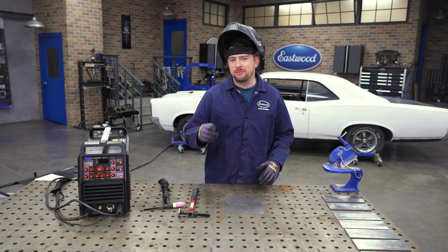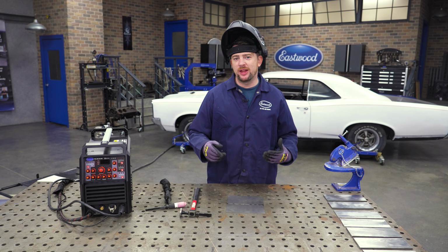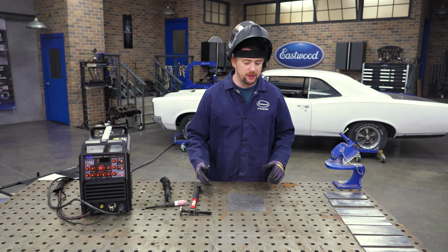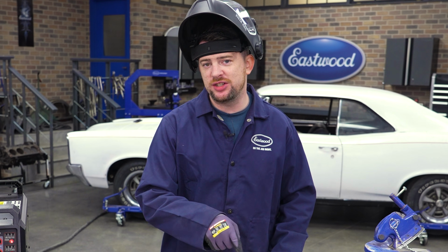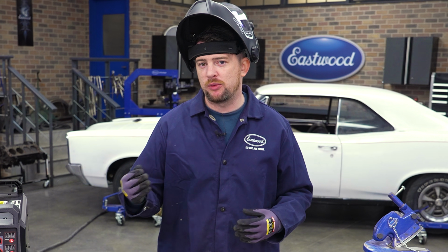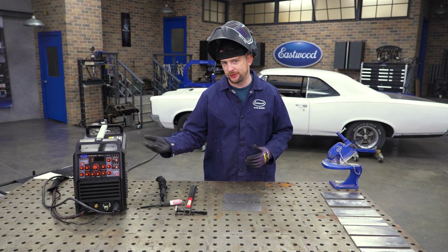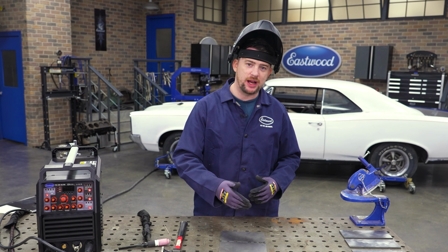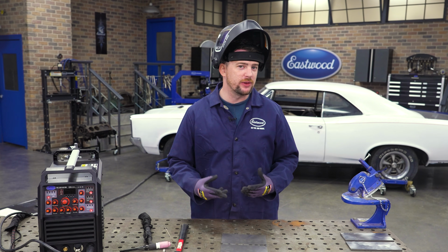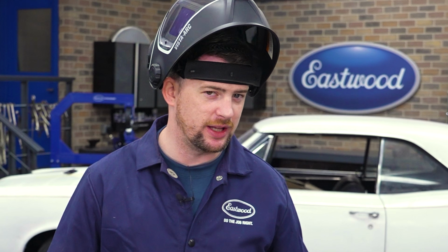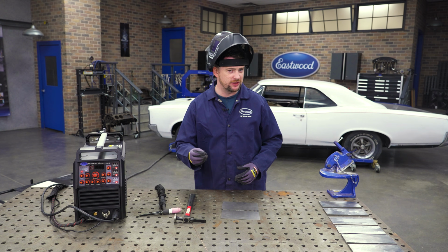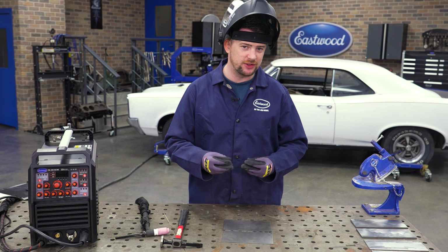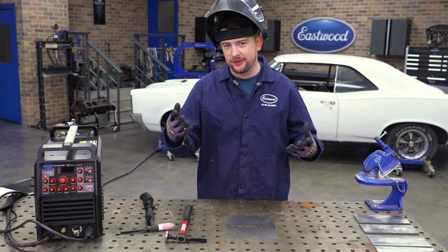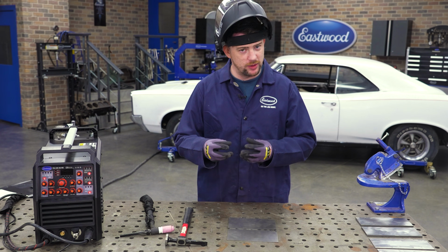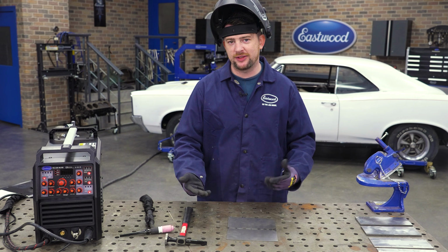The reason I'm tacking the metal down right now is because metal likes to expand when you heat it up. So if I go through and stitch it down, that'll lock it in when I run my bead with the pulse. You'll also see that I hammered these tacks back down. It's important to think of metal as more of like a really tough clay instead of like a really solid object. It's not so much brittle as it is ductile. When you weld, your heat expands, and as it cools, it contracts, it shrinks. So it's important to planish these tacks back out to get the panel to relax and lay flat on the table.